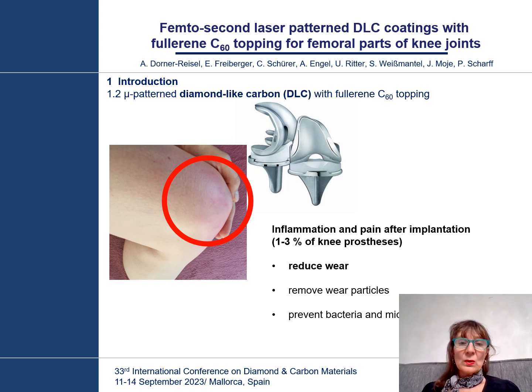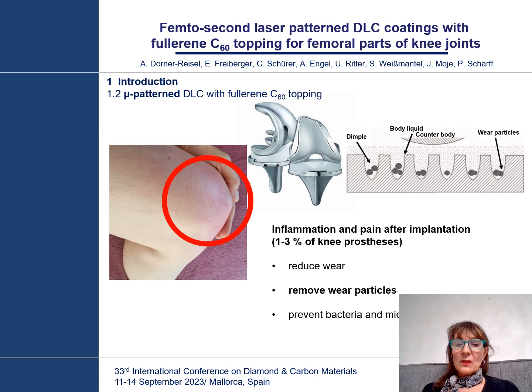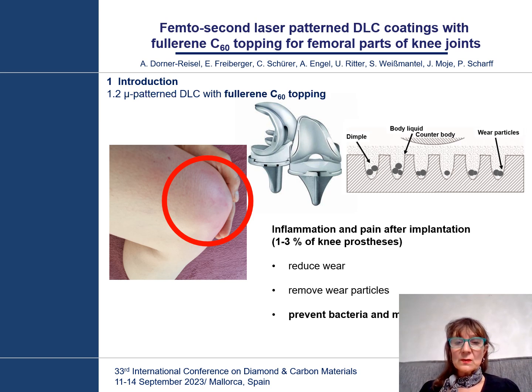We suggest to apply a diamond-like carbon coating on selected parts of the implant. We suggest to apply a micro-patterning on several sections of the implant, and finally a fullerene C60 topping could prevent or reduce bacteria and microbe growth because C60 can act antiseptic.